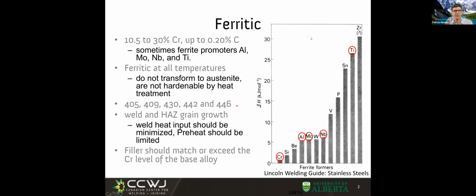These steels essentially connect the delta ferrite with the alpha ferrite, and they do away with the gamma in between. So until you melt them, these steels are ferrite. Can you do heat treatment to them? Well, I'm saying you can't. Of course you can't, because the cool thing of the heat treatments is you get into this new phase that is austenite, the hot phase, and then when you cool down, this hot phase decomposes and gives you different microstructures with which you can play games, and will give you different mechanical properties.